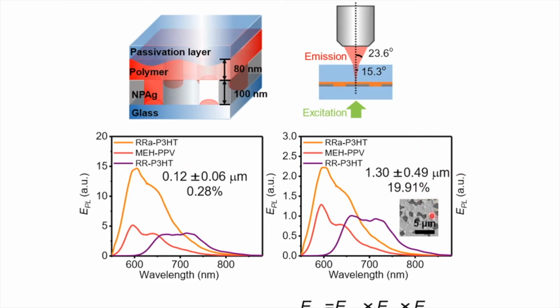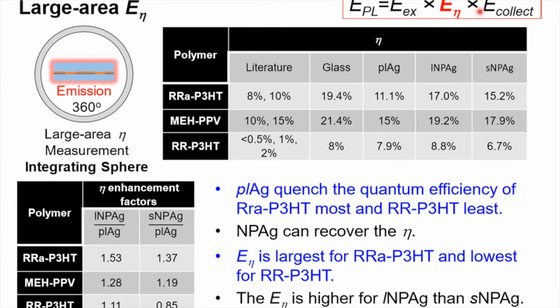However, for the large pore sample, you can see that the overall enhancement was less. And in general, the smaller pores tended to enhance the emission the greatest due to more intense localized surface plasmon resonances. The enhancement in the photoluminescence is caused essentially by either an enhancement in the excitation rate, an enhancement in the quantum efficiency of the material, or an enhancement in the collection direction. To remove the directional dependence of the potential emission enhancement, we studied the quantum efficiency modifications by inserting our samples into an integrating sphere. So here we remove any directional dependence of our measurements and actually determine if there's a quantum efficiency enhancement caused by the metasurface on the polymer.